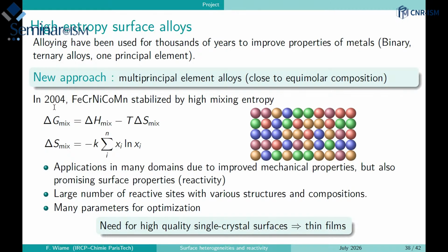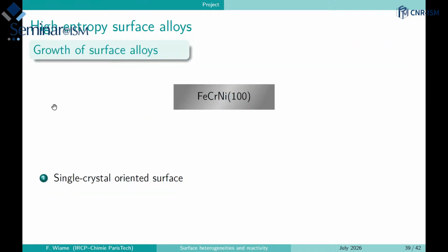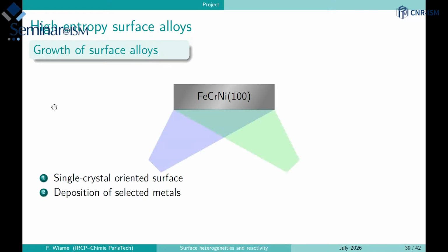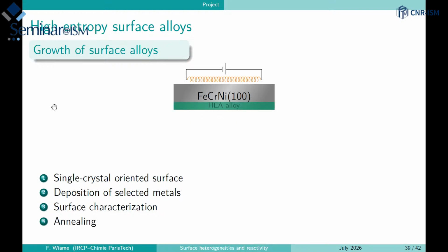And so the idea is that if we want to apply our surface science methodology to this, we need to have very good quality surfaces, which for the moment is not really the case. The idea is to create nano thick films of high entropy alloy. You've seen that the Cantor alloy is iron, chromium, nickel, cobalt, and manganese. So if we start from stainless steel, we could imagine that we can deposit some selected metal at the surface, and by annealing, produce some surface alloy and characterize all of them.